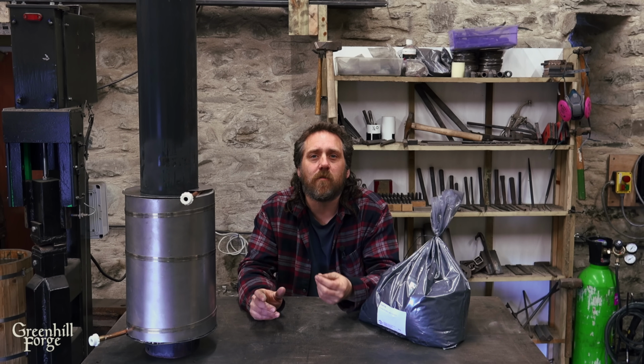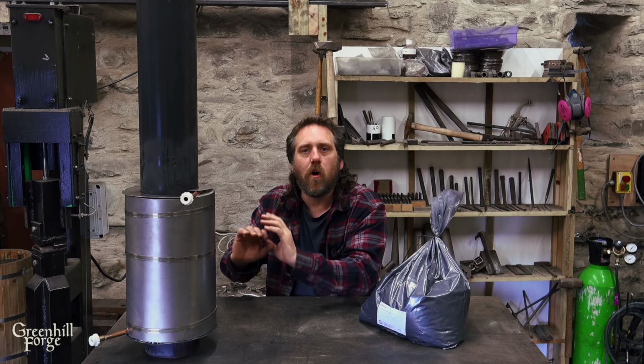It's also incredibly non-reactive, so it's not gonna be interacting with the steel or the copper. It's fairly neutral. It's also gonna form a little barrier in between the copper and any exposed steel, so it'll actually help reduce galvanic corrosion between those two metals. You can get it in a big variety of grain size, so this is really fine and it's just gonna fill in all the cracks really easily. Also, because of how non-reactive it is, you won't run the risk of having a thermitic reaction.